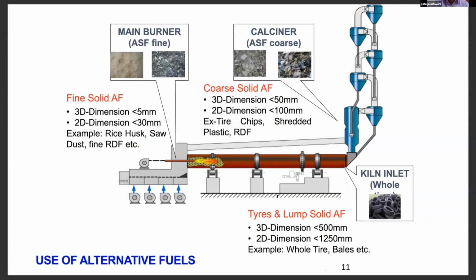Now these alternate fuels can be fired at various locations in the rotary kilns. The coarse fuels having 3D dimension of less than 50 millimeter can be fired in the calciner. And finer solid fuels can be fired inside the rotary kiln where the 3D dimension will be less than 5 millimeter and 2D dimension can be less than 30 millimeter. So fine fuels like rice husk, sawdust, or finely shredded or finely crushed RDF can be fired inside the rotary kiln main burner, while the coarse tire chips or shredded plastics or coarse RDF around 50 millimeter size can be fed into the main calciner of the rotary kiln process.